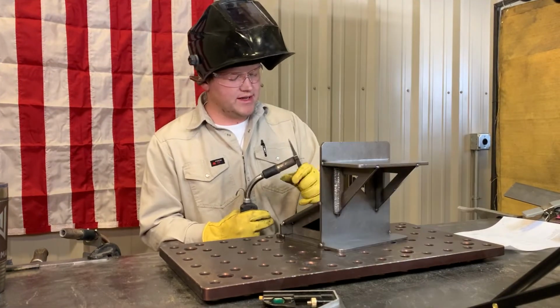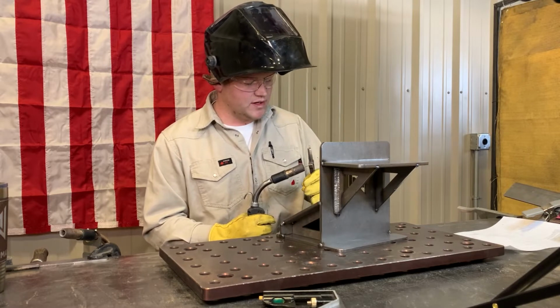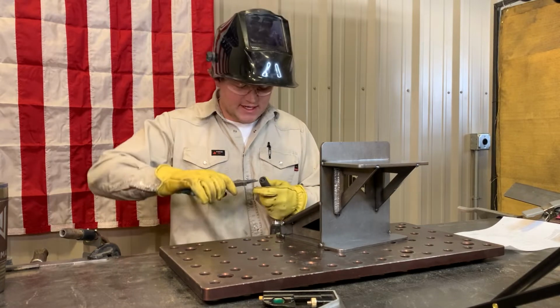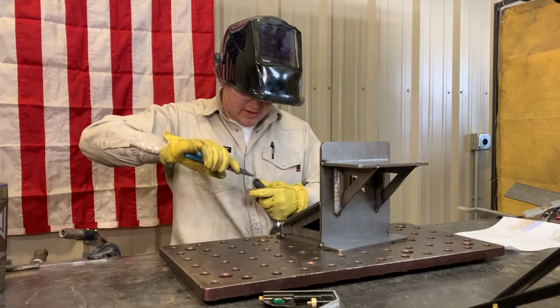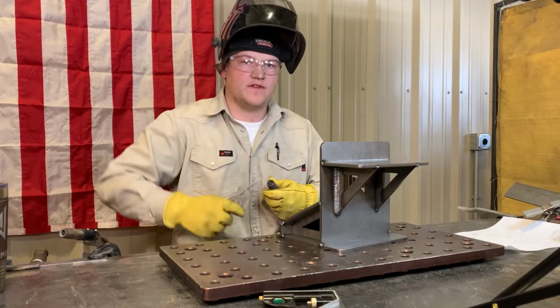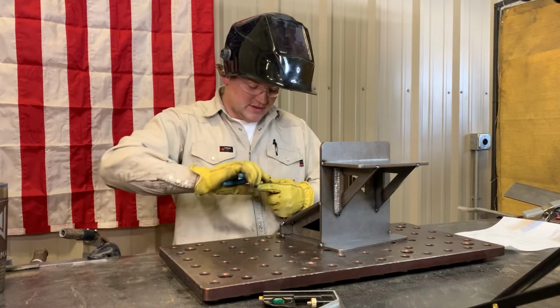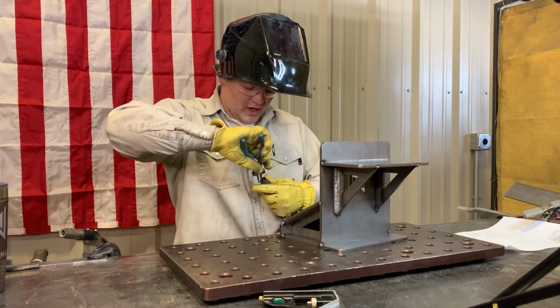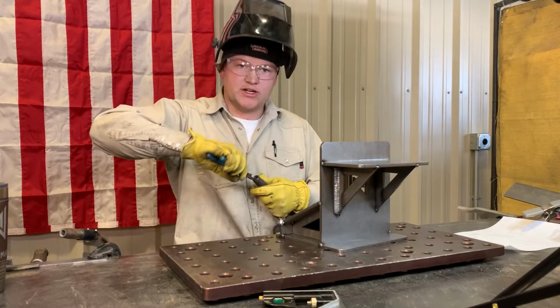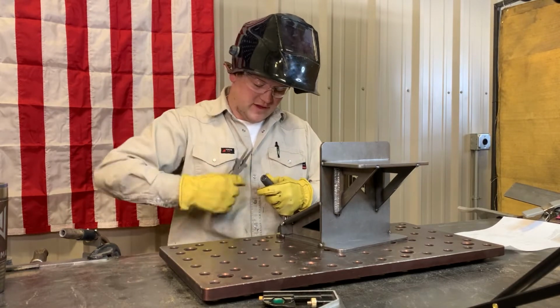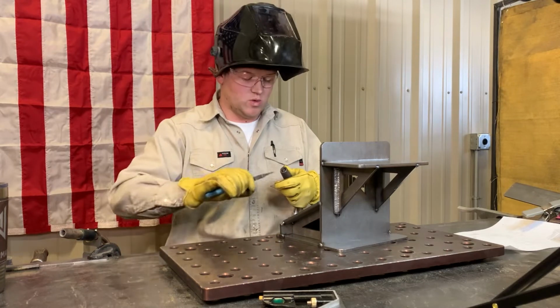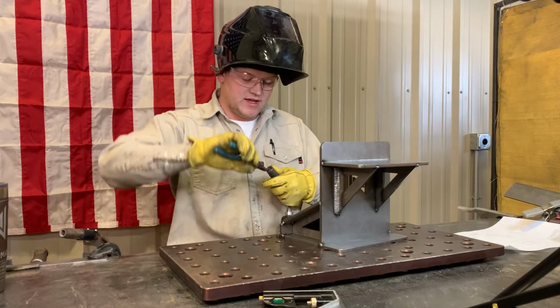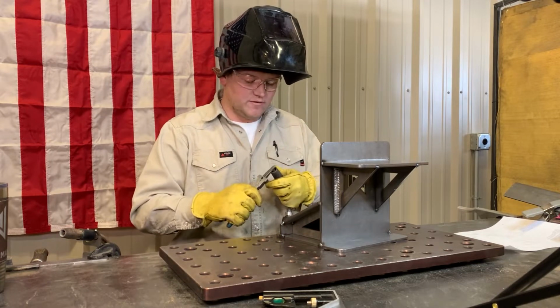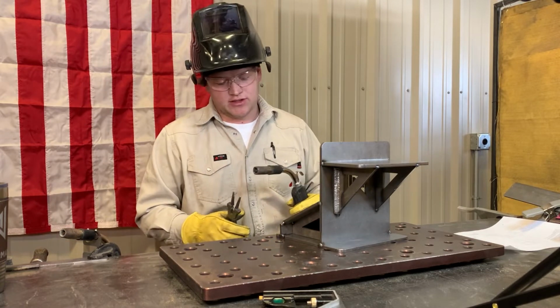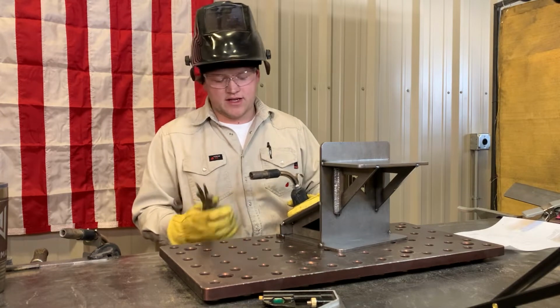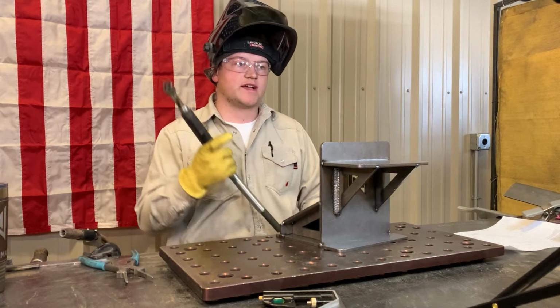A really big tip in having a successful weld with any wire feed process is keeping your gas nozzle and your contact tip very clean. Two reasons. One reason is that your gas nozzle is what guides your gas flow and is what shields your weld puddle. So if you have a very dirty nozzle, it's going to affect your gas flow, which then will affect the gas shielding of your weld. And if you don't have a good shielding gas over your weld metal, then it's not going to weld very good. You're going to get porosity, worm tracks, and stuff like that.